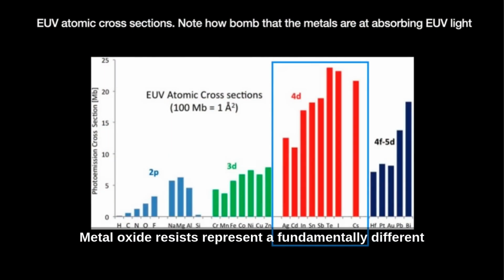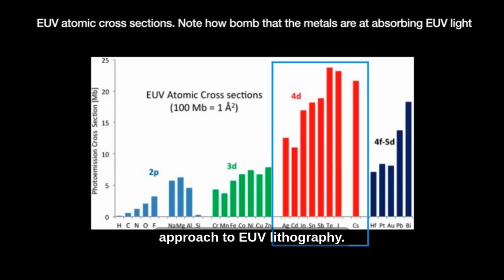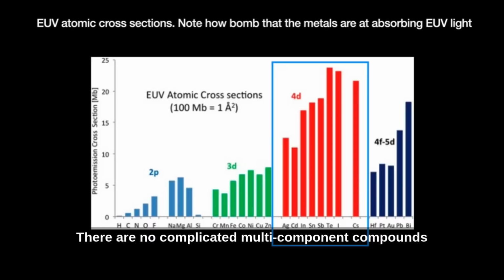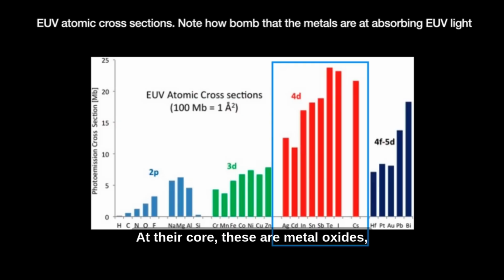Metal oxide resists represent a fundamentally different approach to EUV lithography. Unlike CARs, these resists change directly when hit by an EUV photon. There are no complicated multi-component compounds and no chemical amplification effects. At their core, these are metal oxides, typically zinc or tin oxide, attached to organic molecules. The key advantage is that metals have much higher Z numbers than the carbon, hydrogen, and oxygen that make up traditional CARs. This makes metal oxide resists 4 to 5 times more sensitive to EUV photons than organic CARs.